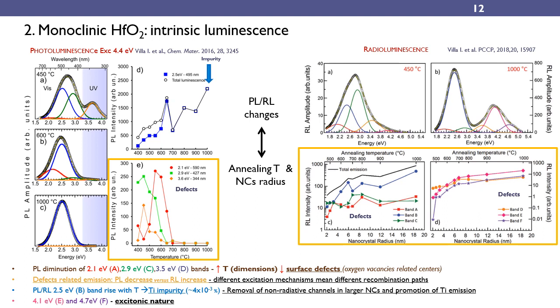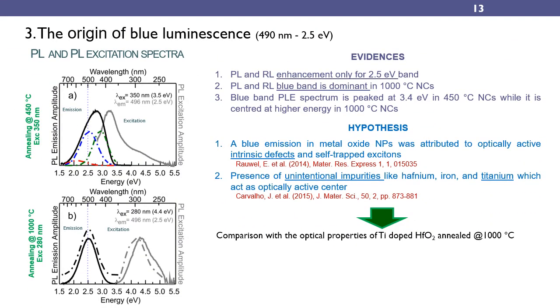The photoluminescence and the radioluminescence increase of the blue band reveal that these bands can have a different origin, and especially it can be related to the presence of impurities in the lattice that can be activated during the annealing temperature increase. Among impurities, titanium is the most probable in the hafnium oxide lattice. So, by now we know that besides the intrinsic bands, there can be a blue band associated to an accidental titanium impurity in the lattice, whose intensity is dominant in the spectra of samples treated at high temperature.